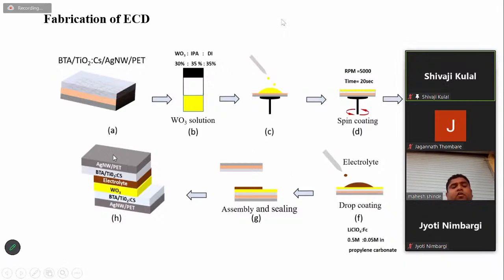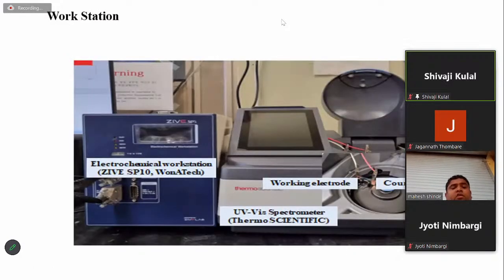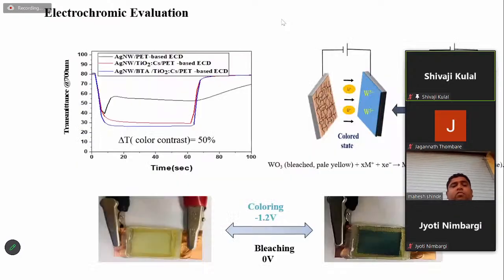And this is our fabricated electrochromic device. This is the TCE silver nanowire, this is the passivation layer, this is the electrolyte, this is the tungsten oxide, and this is the counter electrode. This is the structure of my fabricated electrochromic devices. And this is the workstation I use for the measurement, of how much the color changes and how much time it takes for the coloration. So this is the result.